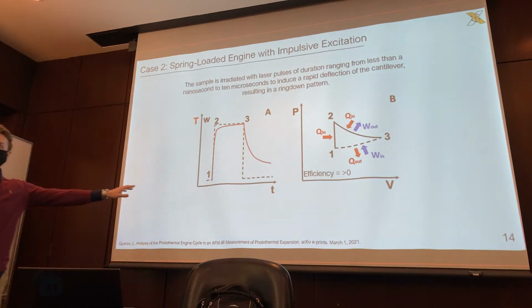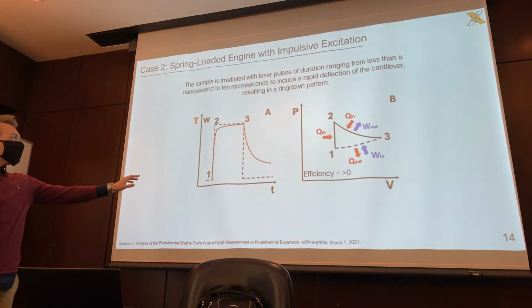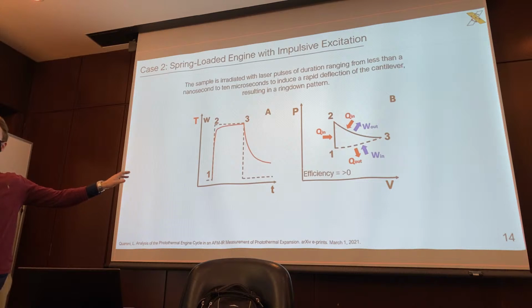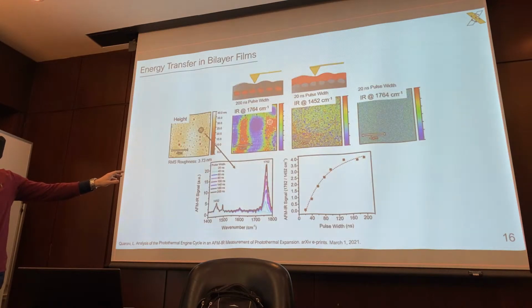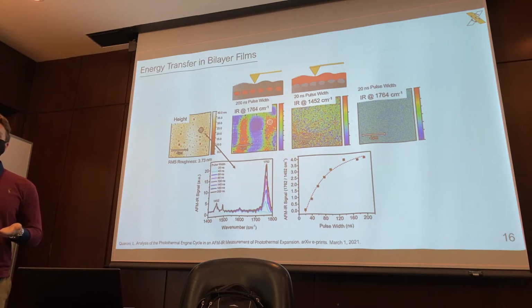So for shorter pulse widths, your sample will not be irradiated for long enough to actually create the maximum amount of expansion that you need to detect it. And so going back to here, this is exactly what we saw: for short pulse widths, we could only detect the top surface.